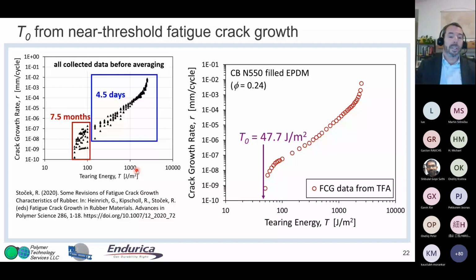However, as you start to approach the really slow crack growth rate end of the curve, now it starts to take months. And so this is all the raw data that were collected, and then those were averaged to give this crack growth curve that I show over here. And what you see is the power law region, right, with slope F, upturn towards tearing, right? Eventually this is going to tear.